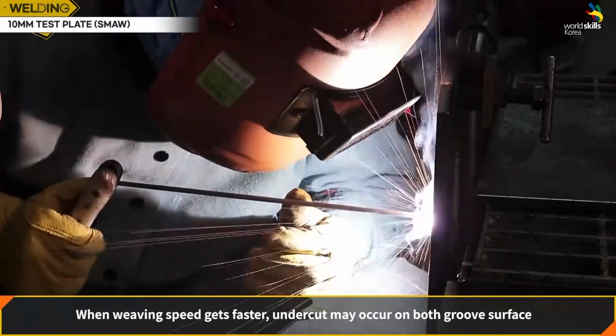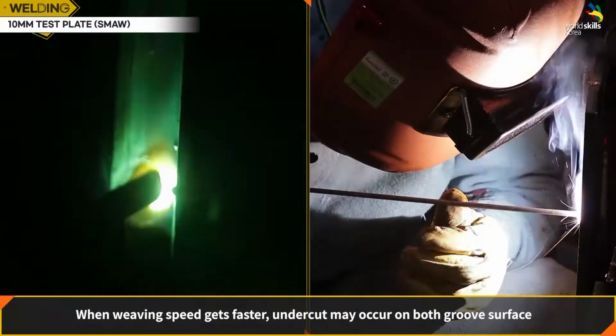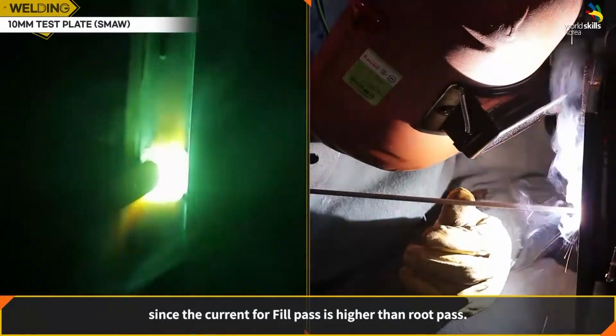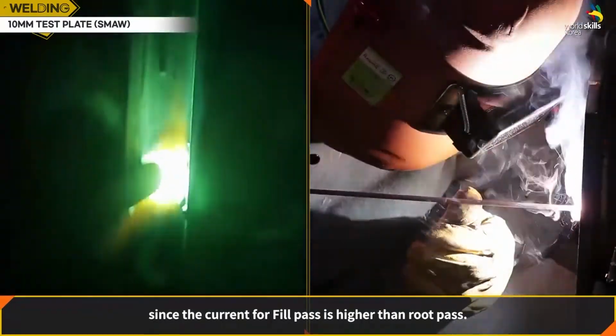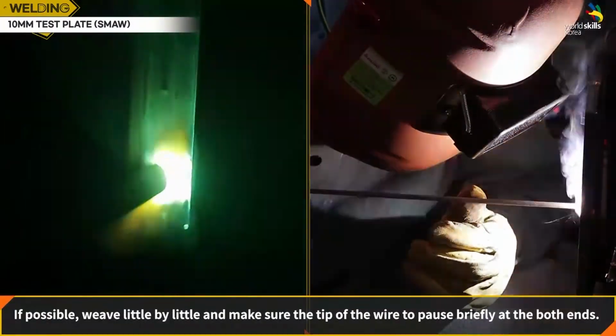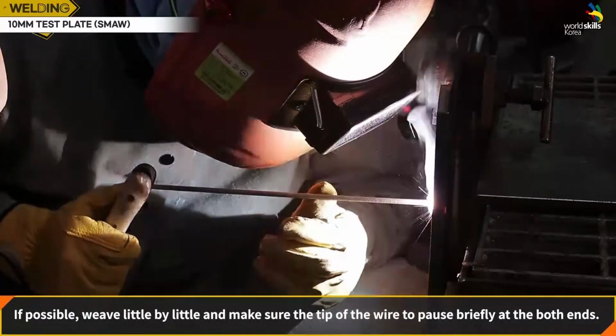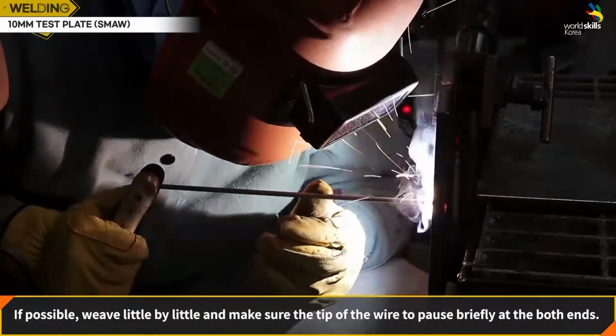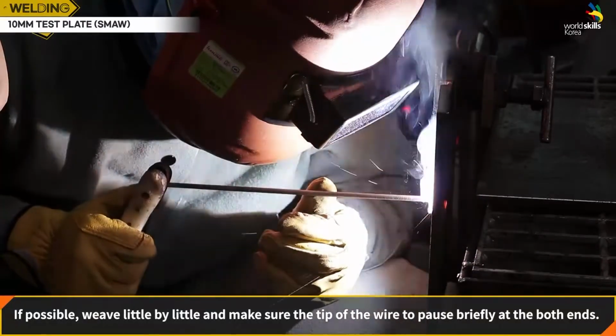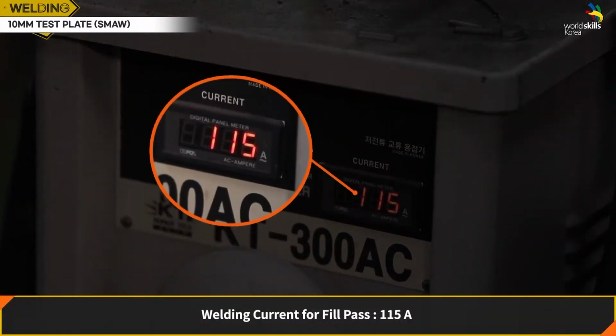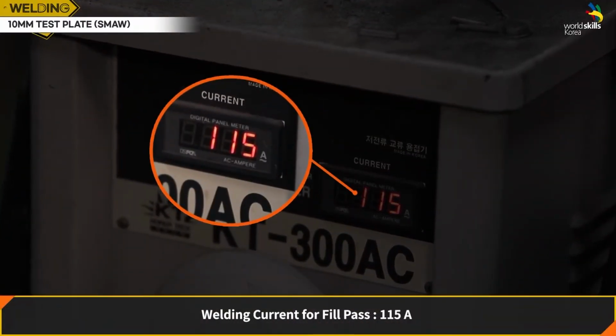When weaving speed gets faster, undercut may occur on both groove surfaces since the current for the fill pass is higher than the root pass. If possible, weave little by little and make sure the tip of the wire pauses briefly at both ends. Welding current for the fill pass is 115 amperes.